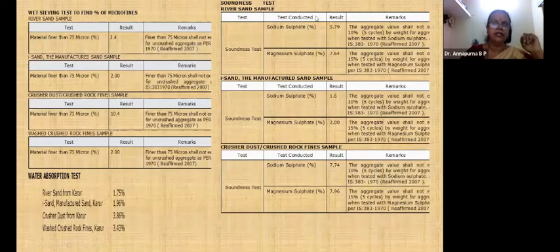This is the soundness test. When the sample is reacted with sodium sulfate or magnesium sulfate, the aggregate value should not exceed 10%. So here for river sand, it is 5.79 and 7.64, about 6.764. And for manufactured sand, it is 1.6 and 2. It is lesser than the river sand.